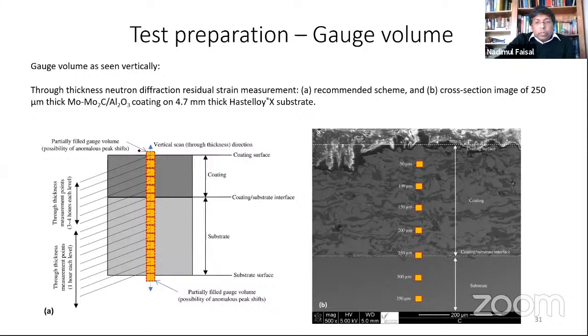Right, so one of the things to worry about is the volume you are going to investigate. So assume this is your coating, and that is your very thick substrate. Focus on the coating part. If you have a beam going to this space, this is the surface above, it is open space. So you don't have to measure that bit, but you have to submerge the beam inside the coating. So how deep should you be?